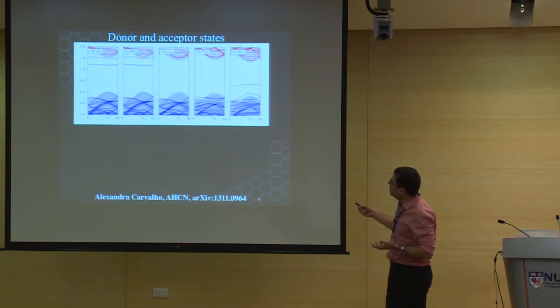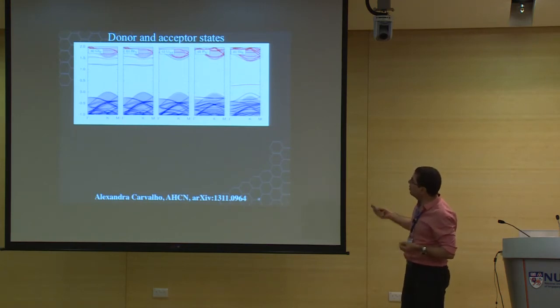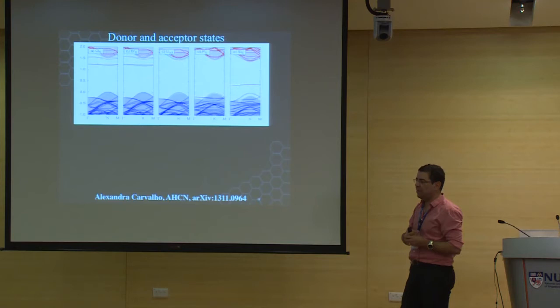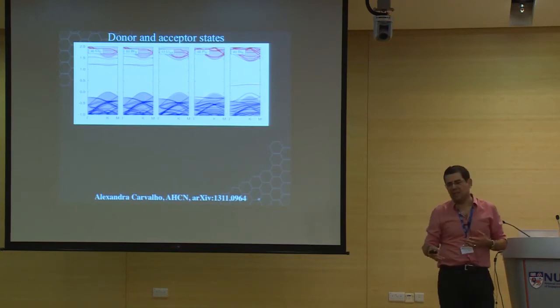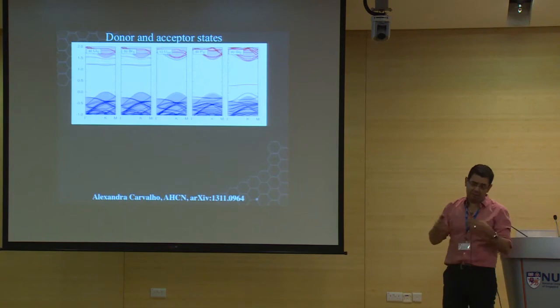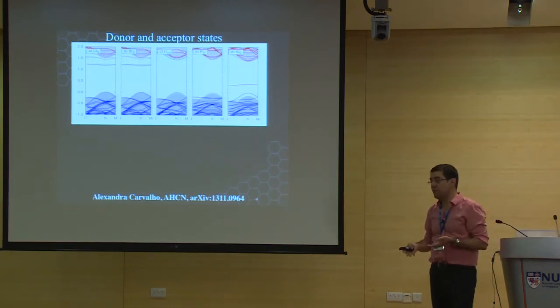You can see that lithium adsorbed on the surface of these chalcogens can create very shallow states, or if you replace, for instance, sulfur by silicon, you can get very deep states inside of the band. So essentially, the way you can manipulate donor and acceptor states in a traditional semiconductor heterostructure or device, you can do here by doing these chemical replacements.